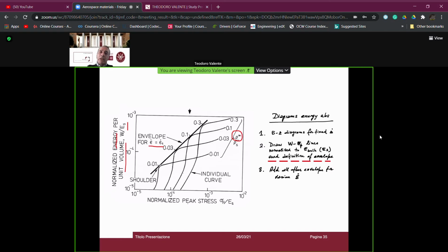draw the envelope which, for each condition, that is the maximum, puts together all the maximum values, corresponding to the couple between the normalized energy per unit volume and the corresponding peak stress. And this is made just for one value of the strain rate.